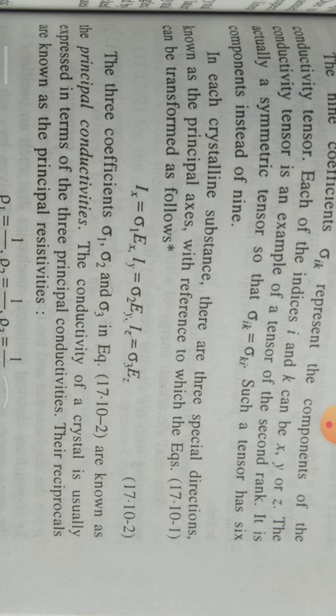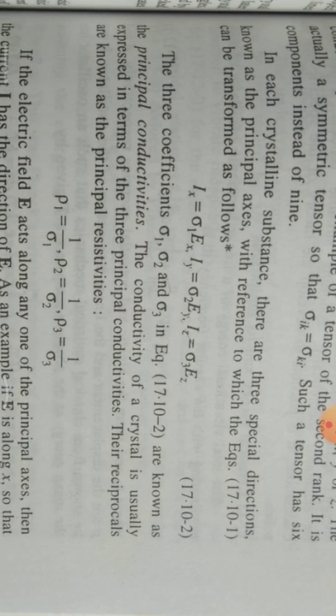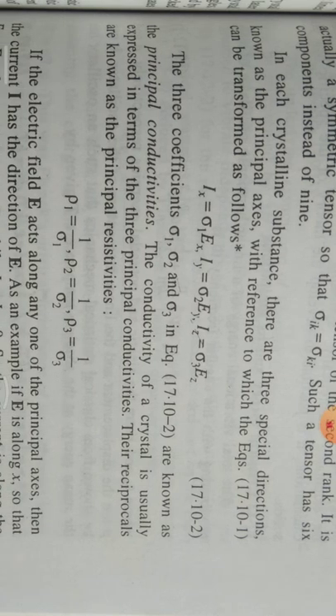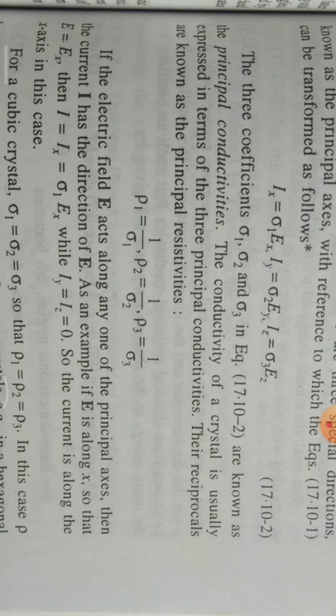In each crystalline substance, there are 3 special directions known as the principal axes, with reference to which the equation can be transformed as follows. Ix is equal to sigma 1 Ex, Iy is equal to sigma 2 Ey, Iz is equal to sigma 3 Ez. The 3 coefficients sigma 1, sigma 2, sigma 3 are known as the principal conductivities.